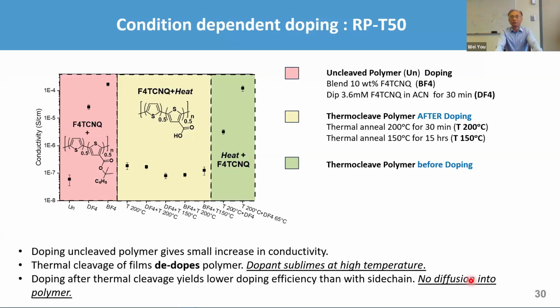So now if you do the doping, remember doping, you need a dopant and you need a conjugated polymer, and you mix them all up. Some redox chemistry is going to give you the charge carrier density, then you end up with the conductivity. So F4TCNQ is a strong oxidant, which we often use to get the polymer p-type doped.